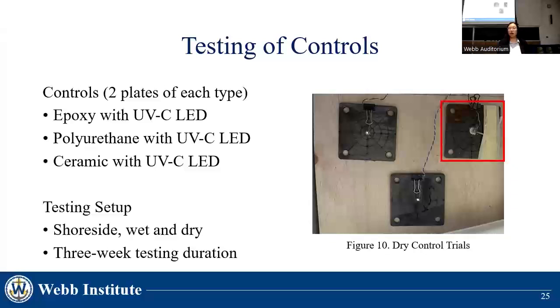During the implementation of the primary and control trials, it became apparent that ceramic posed several challenges to construction. Specifically, the ceramic coating was unable to produce a flush surface and proved too delicate to support the electrical components. Due to these challenges, ceramic was found to be unsuitable for our experiment, and it is not fully examined in our results. Controls testing indicated no significant degradation of coating quality over a 3-week testing period.